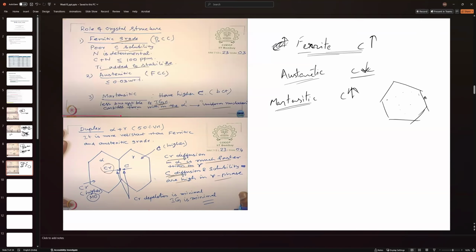So what will happen? You form precipitates, but since the diffusion of most of the chromium is coming from the alpha phase, a relatively small amount of chromium is consumed near the grain boundary due to this precipitation, right? So overall diffusion from the bulk compensates the region around the precipitate. So suppose this is your precipitate and this is your region around the precipitate where you had low chromium. So this is your chromium carbide.